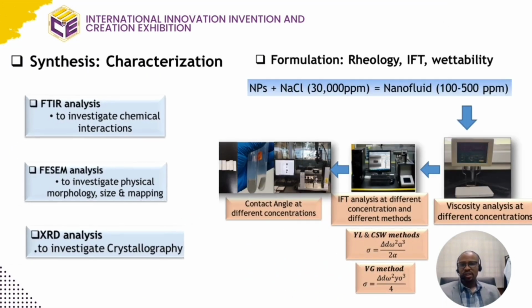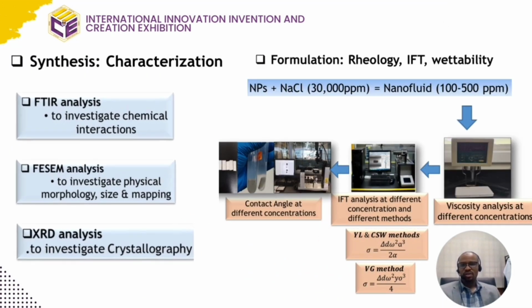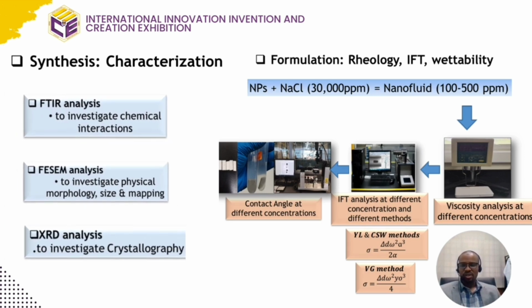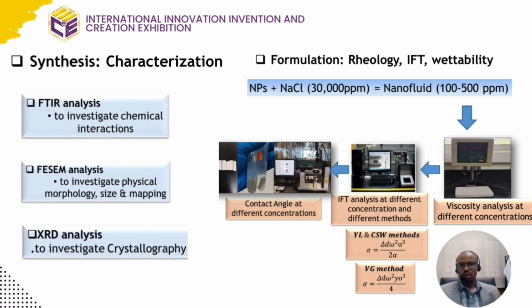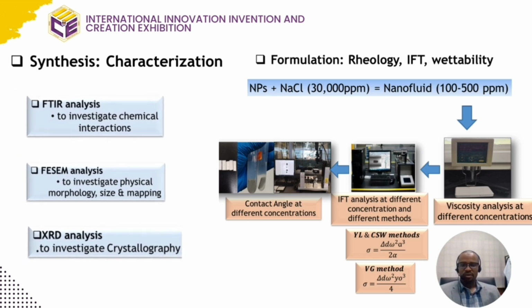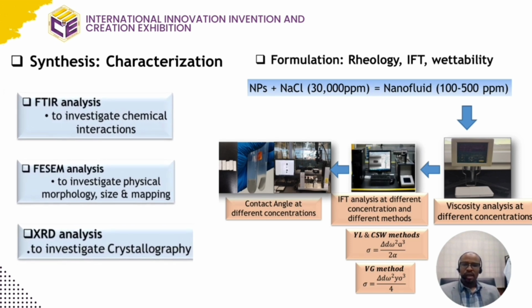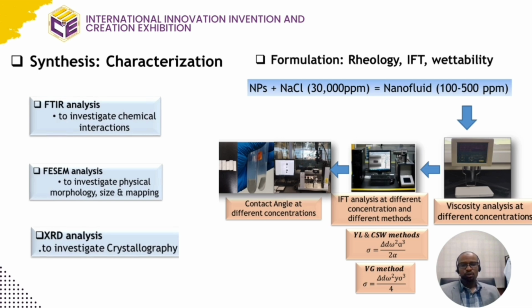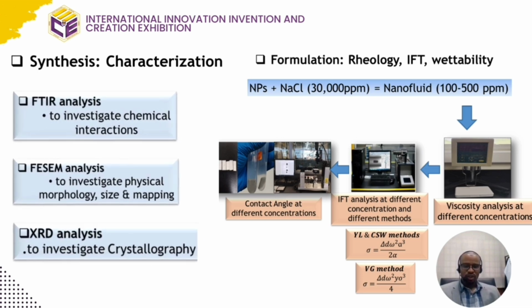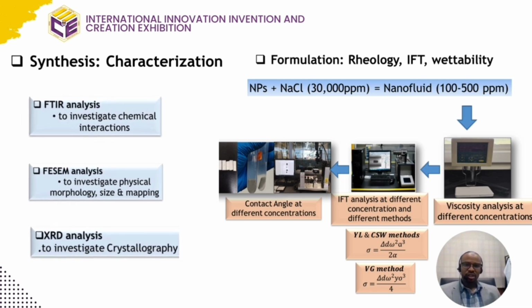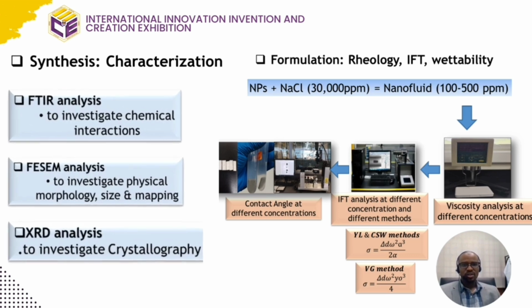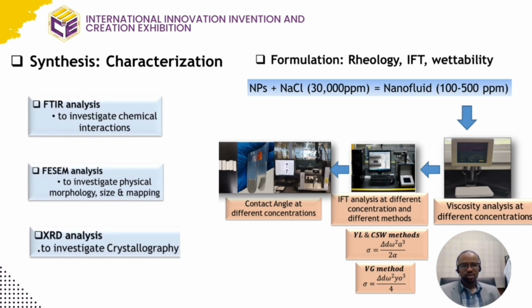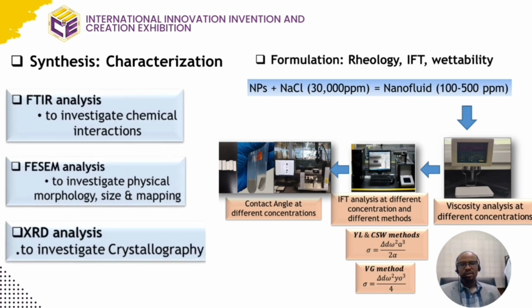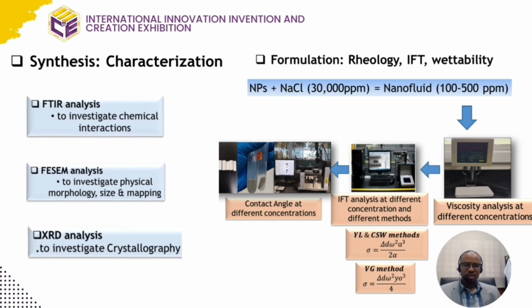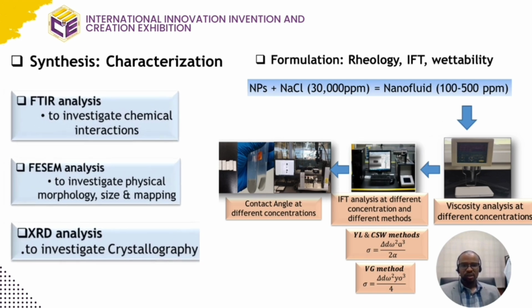So subsequently, the product was further characterized to understand the chemical interactions between the composite nanomaterials, such as FTIR, FESEM, and crystallography. After that, we also formulated the nanofluid, which is a base fluid that can be injected into the reservoir. So we started by checking the viscosity, as you can see from the first image, and then checked the interfacial tension, and then also investigated the contact angle.